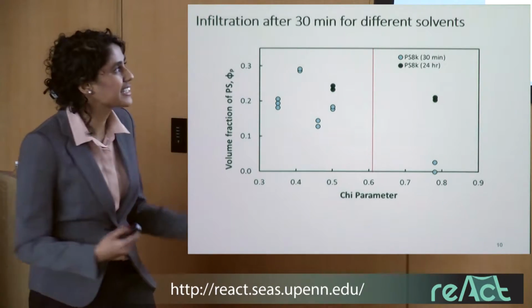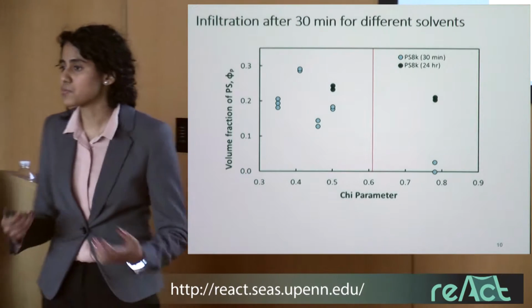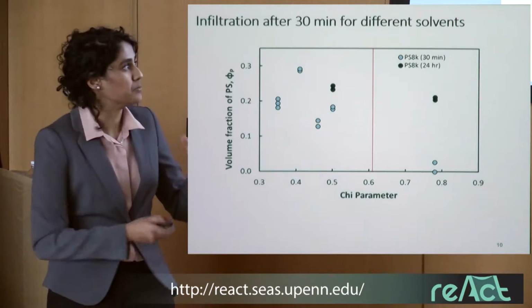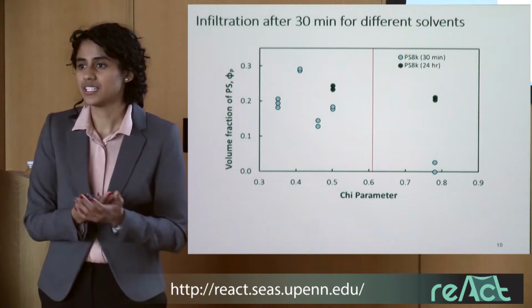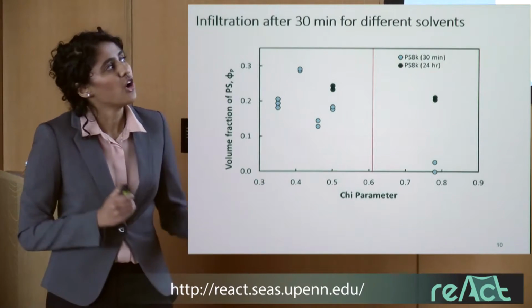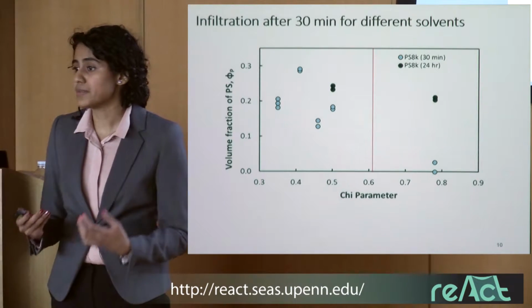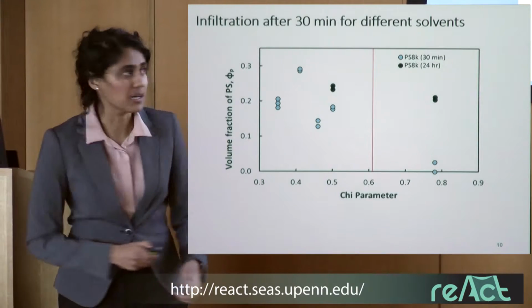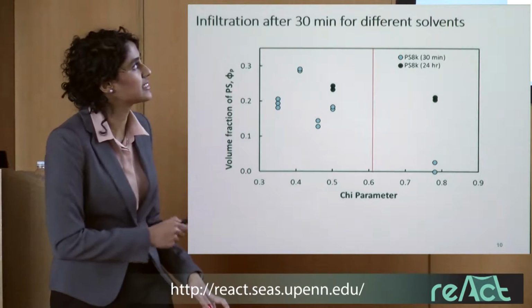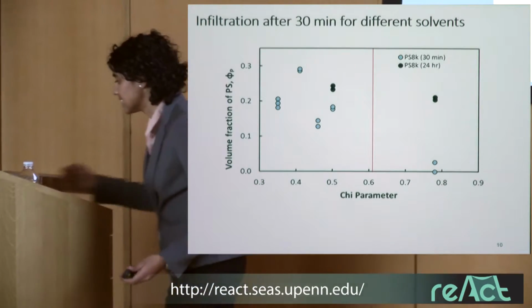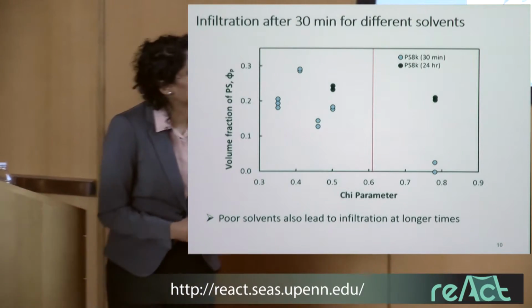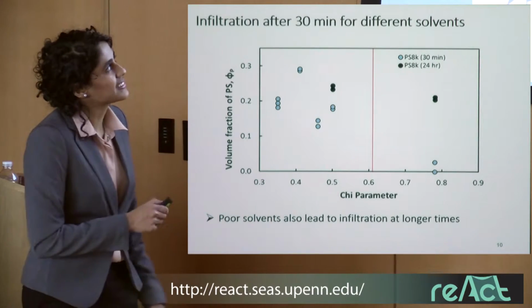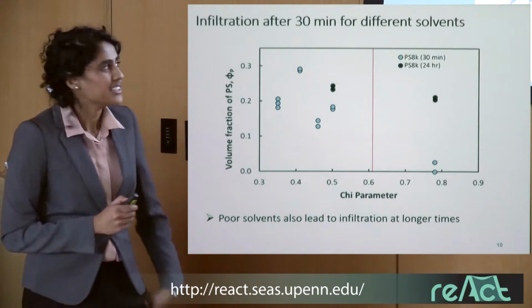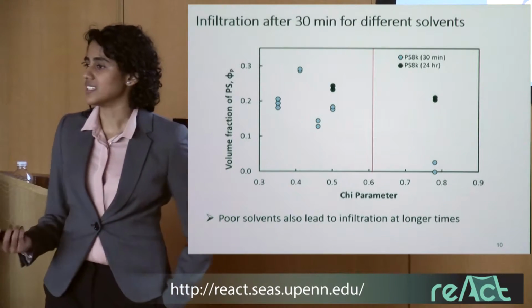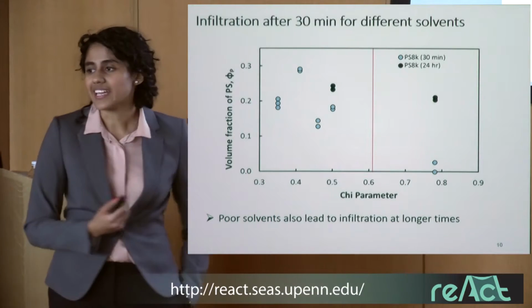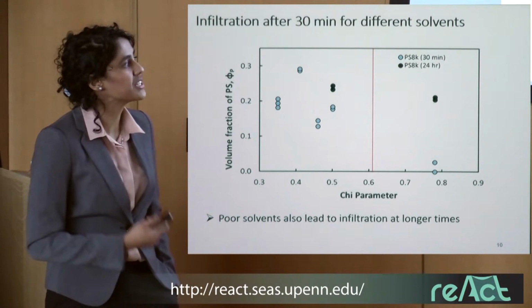So this indicates to me that either there's some inherent property in the polymer solution solvent system that slows this process down, or there's a different regime, maybe a surface-driven regime, that leads to infiltration in this case versus these cases. So this was really exciting and interesting because we weren't sure that this would occur. So what we thought was we could maybe exploit this in some way to make the system even more interesting.